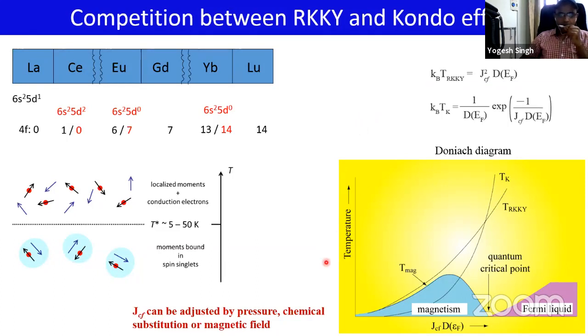So qualitatively, if you draw temperature versus this J interaction between the conduction electron and f electron moments, then you see that the Kondo temperature rises exponentially, whereas the RKKY interaction rises as the square of J. And therefore, for small J, the magnetic order wins. But as you increase J, the Kondo effect quenches the moments, and therefore you lose magnetic order and reach a quantum critical point. So this is the qualitative understanding of how quantum critical points can arise in heavy fermion materials or Kondo lattice materials.